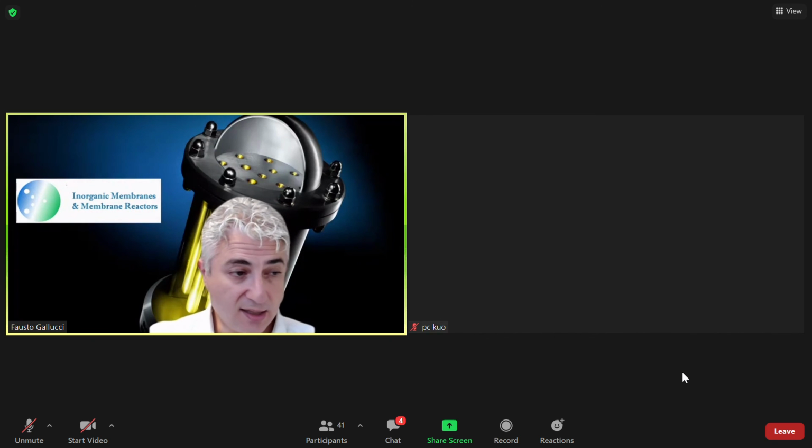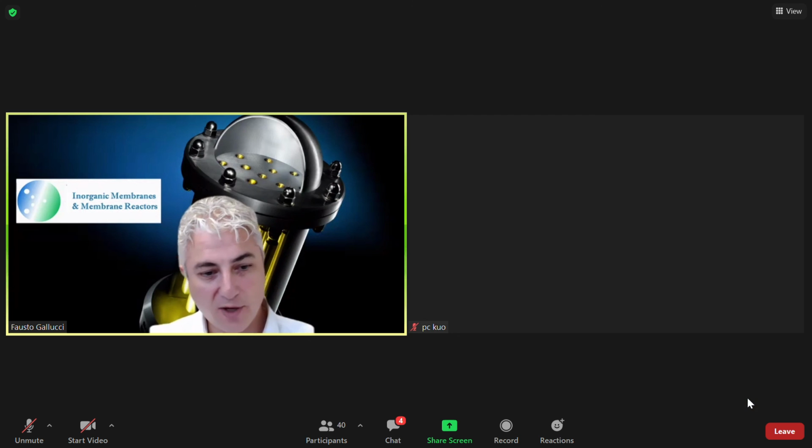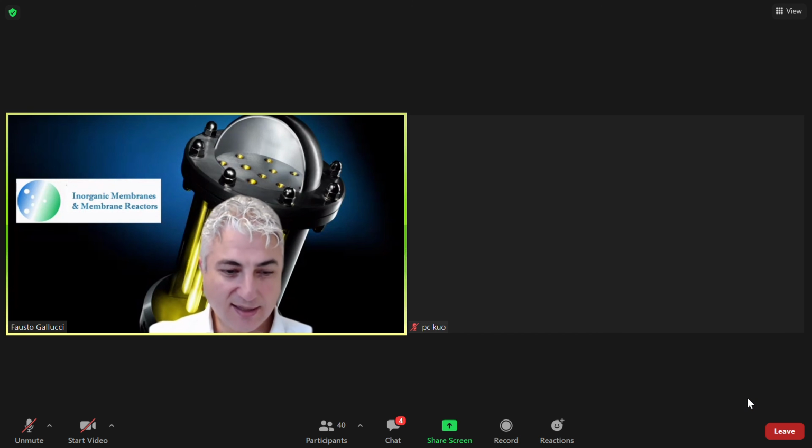For example, if you take the reforming or the cracking of ammonia, which we carry out at 420 degrees or even 400 degrees, then there is no problem at all. For water gas shift, there is no problem at all. Reforming of methane, yes, is a little bit problematic.